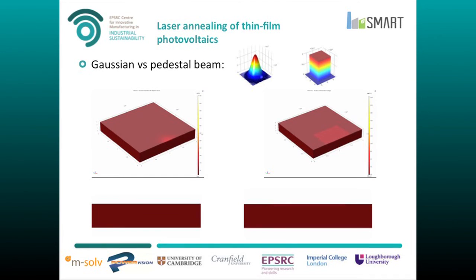So then we run simulations comparing a Gaussian beam to a pedestal beam, which is a circular Gaussian spot versus what is essentially a flat square, and we get this. So here we have a circular spot, lots of heating in the center versus very little heating on the outside. And it's much narrower than this one, even though the beams are actually the same width, because the heat effect on the outside of the beam here is not enough to actually warm the substrate up.